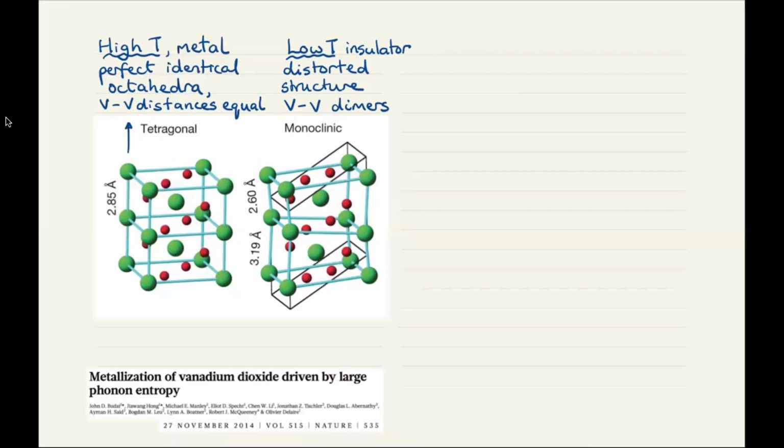So one again has the question of whether one's seeing really a Mott transition driven by the Coulomb interactions between the electrons, or there's a structural transition as the primary driving force, and then the electrons localize in the new atomic orbitals. So can we explain this insulating behavior by just using a simple linear combination of atomic orbitals picture within really a single electron approximation, not taking into account electron-electron Coulomb interactions, but just taking into account the bond alternations?